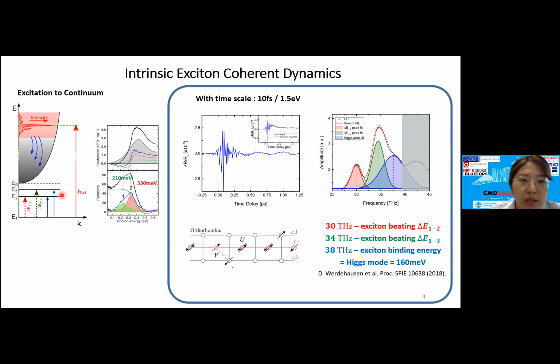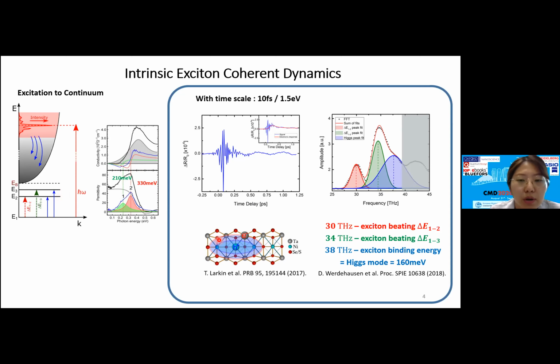It's already discussed in the static optical measurement. There, we suspect there are polaronic complexes in the system. So it's worth trying to see the phonon dynamics in the system to see the relation between this exciton condensation and the lattice. So we pumped with a longer time scale pulse to see the coherent phonon mode.